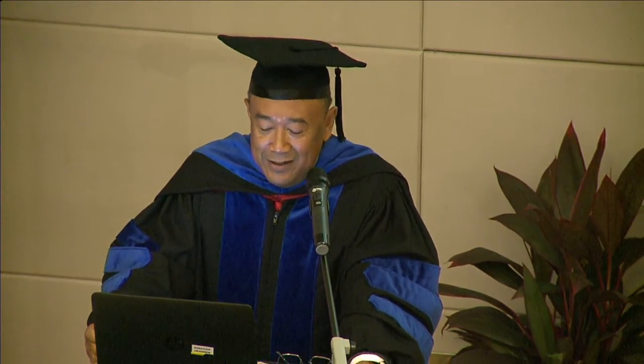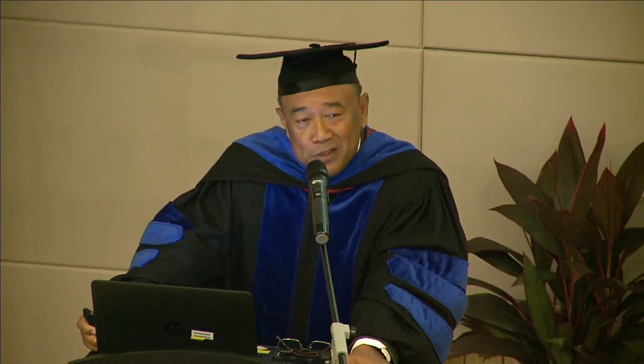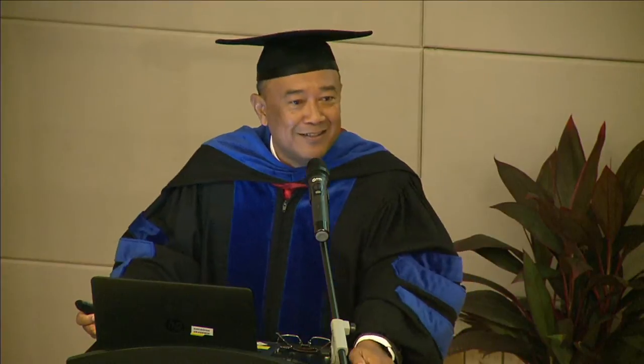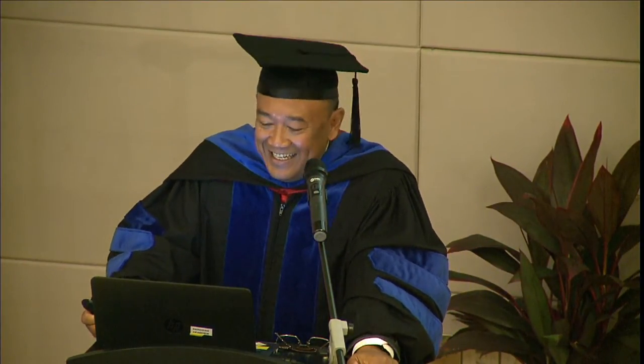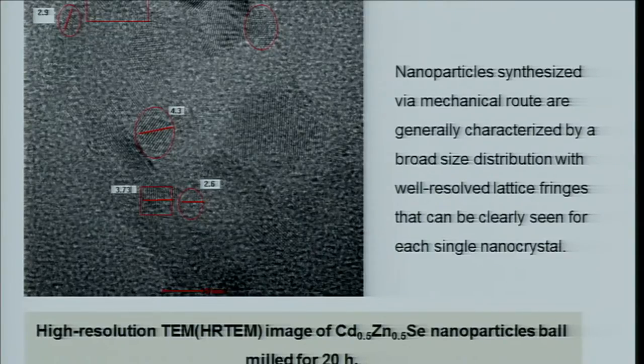take this sample and look through another type of instrument, which we call the HRTEM, the High Resolution Transmission Electron Microscopy. This type of mode in the TEM allows us to look into the details of the atomic arrangement. And it's quite expensive. And again, we have it in IBS. Again, thank you, UPM, for the support that they give to the researchers here on campus. And we see that we have particle sizes between 2.6 to 4.5 or 5.3 and so on. So those very small particles, which we call nanocrystals, or sometimes people call them quantum dots.